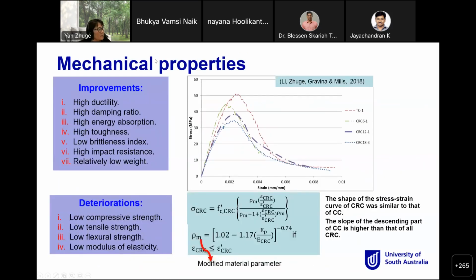Another property we tested was the stress-strain performance. This summarizes the mechanical properties of crumb rubber concrete. The good thing is very high ductility. Using crumb rubber improves the ductility of the materials, and gives a very high damping ratio. So it has very high energy absorption and higher toughness compared to normal concrete, a low brittleness index and high impact resistance, and also relatively low weight. So these are all the good things about crumb rubber concrete.